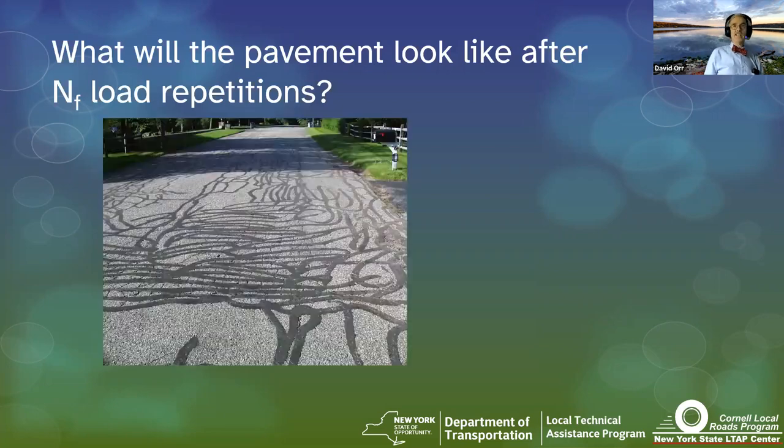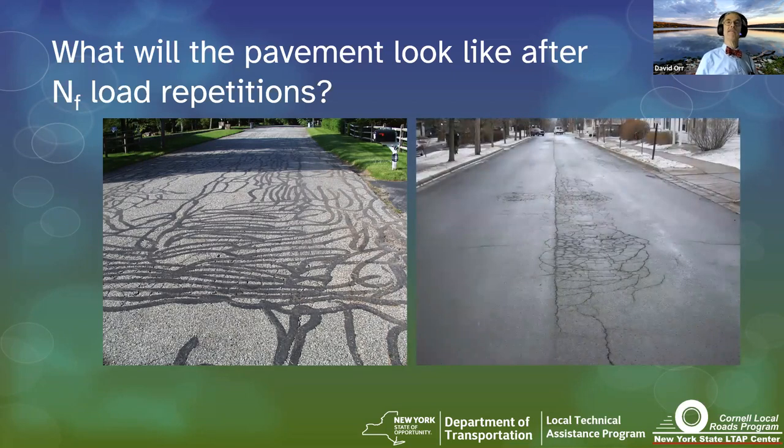It does not look like this. That's well beyond what anybody would agree is a design failure, too many cracks. This is more common, okay? A design failure where we see about 20% of the surface, 25%, and there's debates about that, as cracked. A certain percentage of the surface is cracked. That's a failure in the cracking world, okay? And we could debate what that number is, and you can actually get away with maybe a little bit more in a low volume road.